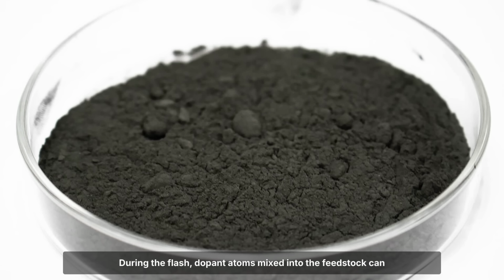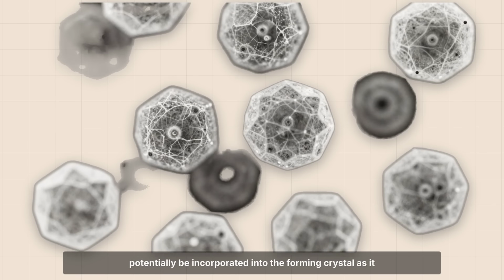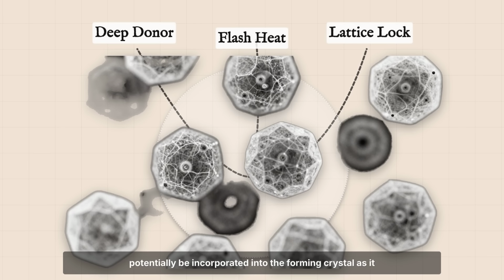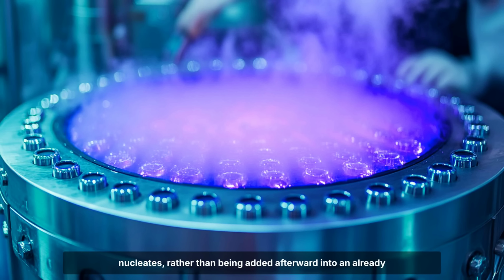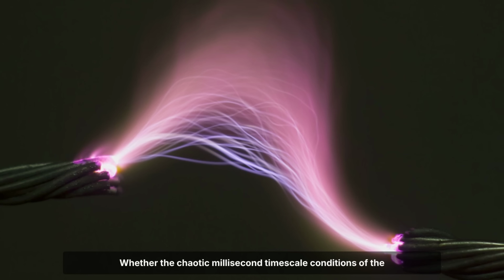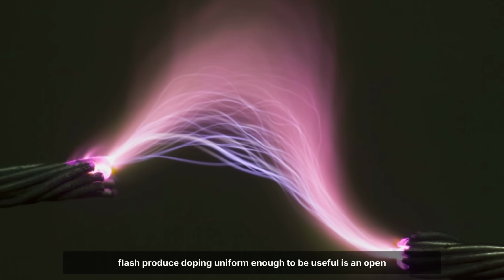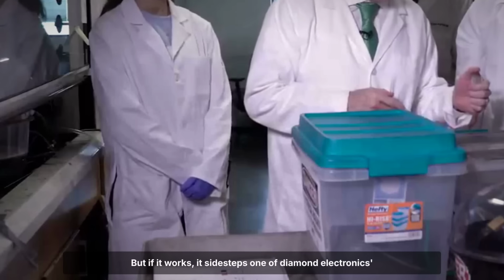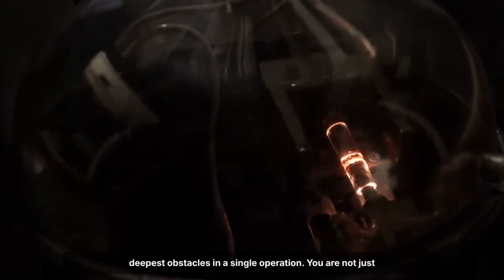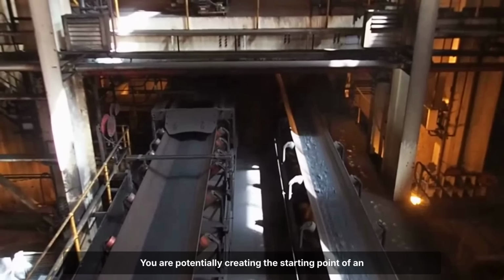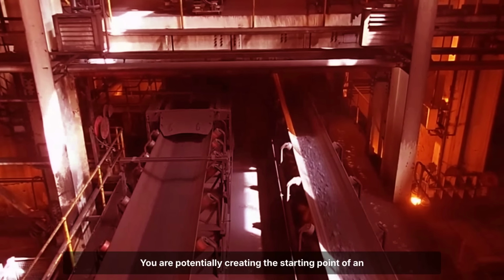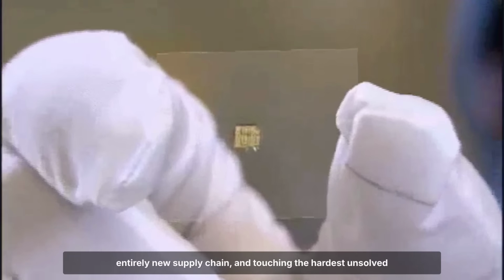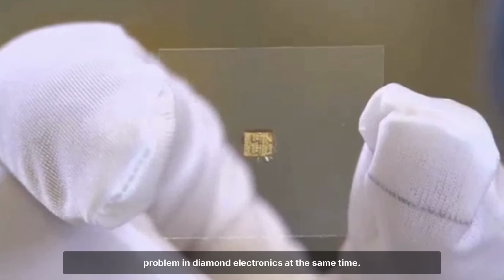During the flash, dopant atoms mixed into the feedstock can potentially be incorporated into the forming crystal as it nucleates rather than being added afterward into an already growing lattice. Whether the chaotic millisecond timescale conditions of the flash produce doping uniform enough to be useful is an open question that the published research has not yet answered. But if it works, it sidesteps one of diamond electronics' deepest obstacles in a single operation. You are not just making diamond, you are potentially creating the starting point of an entirely new supply chain and touching the hardest unsolved problem in diamond electronics at the same time.